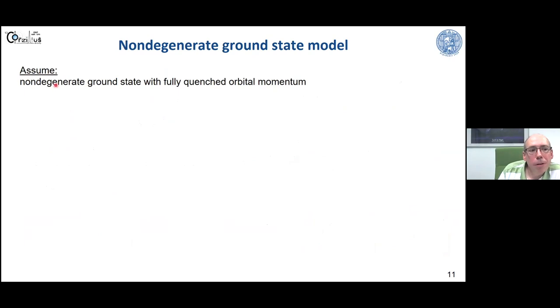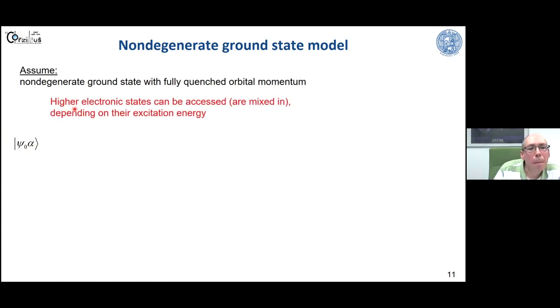So now we assume that we have a non-degenerate ground state with a fully quenched orbital momentum. It's some strong ligand field, or an ion sitting inside a strong ligand field, and no degeneracy. So we have no orbital momentum in this ground state. And with this, we could describe our system as a product of the space wave function of the electron, psi, and the spin wave function alpha. This would be the alpha state, and psi zero would be the electronic ground state.